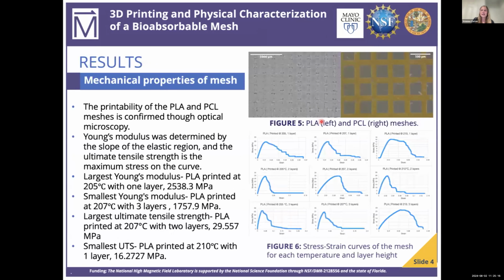And then for the results, so we confirmed the printability over here in figure 5. So the left is the PLA and the right is the PCL material. And then in figure 6, you can see the stress versus strain curves of the PLA mesh at each temperature and different layer heights.